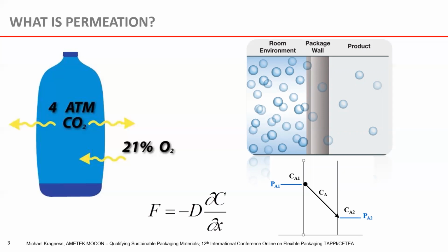And then that brings us to the first law, or Fick's first law of permeation theory. And that says the flux is essentially the volume of a gas that's passing through some medium. In this case, it would be a package sidewall. The flux is really dependent upon the diffusion coefficient of that sidewall, whatever that sidewall is made out of. If that's PET, that would depend on the diffusion coefficient of PET multiplied by the rate of change of the concentration between one side of the sidewall to the other.